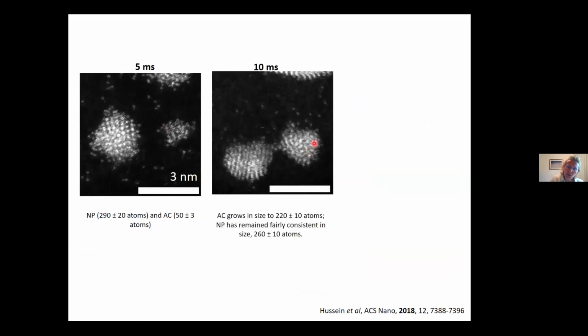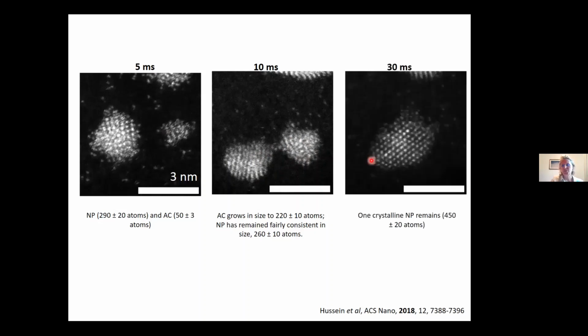This one again, you've got a nanoparticle and an amorphous cluster. And what was nice is we almost captured this bridge formation between the two. So you've got atom transfer between the two states. One of them is going to win out over the other, and you eventually form a combined nanoparticle. So I think these sorts of images were just amazing to us at this level.